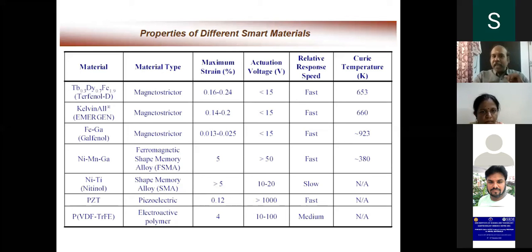The piezoelectric material is good, but the strain levels are much lower compared to your magnetostrictive material, and this is a polymer based material. The only problem with this material is that the temperature capabilities are very poor in this PVDF TrFE. So when you compare all these materials, the magnetostrictive materials have some superiority when compared to other materials. So we have gone for developing these materials in our laboratory.